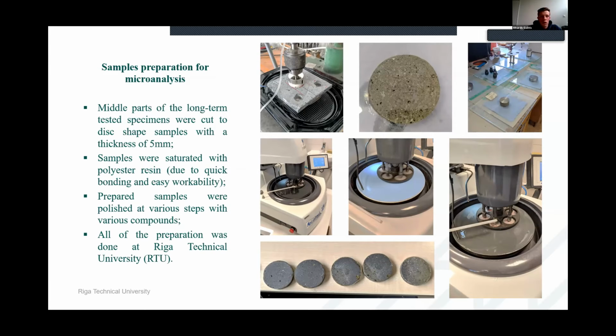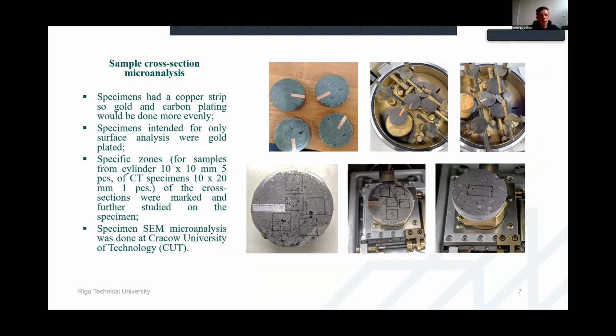And afterwards, the excess resin was ground and polished off from the surface, so that in the end we have a polished section that has its pores and cracks filled with the resin, but the binder and the filler part is just polished and no other materials are on top of it. So the microanalysis was done in the scanning electron microscope. For the tests in the microscope, the samples were plated with gold, so that the plating was done much more evenly.